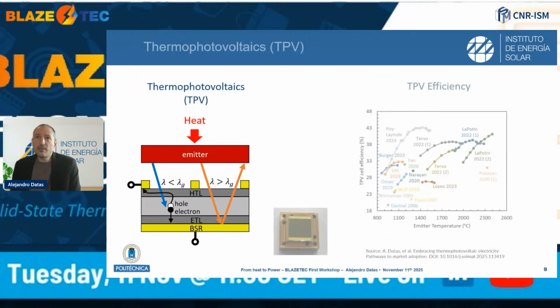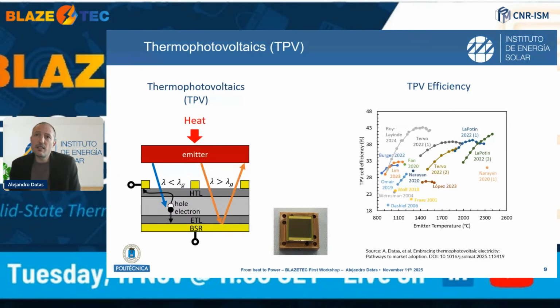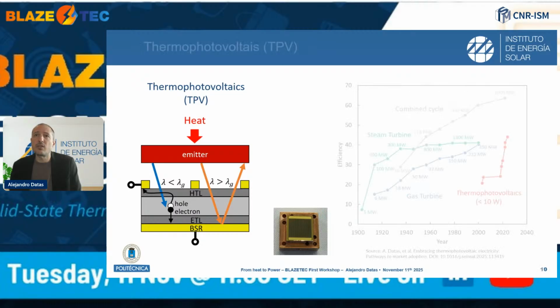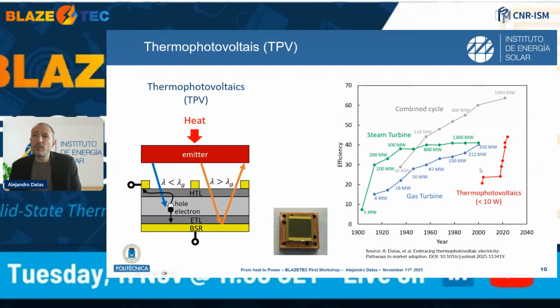And if you look at the different efficiency numbers that have been attained in the last years, you see that several authors have already surpassed 40%. Importantly, also in a wide temperature range. So typically you need very high temperatures, but you can get quite good efficiency almost at any temperature. And this is because of the high quality of the mirrors that have been developed in the last few years. If we zoom out a bit and see what this efficiency means in the context of heat engines, we see that thermophotovoltaics has already reached the efficiency levels of steam turbines or gas turbines. So this is quite a relevant milestone. Of course, it has been demonstrated at lower power levels, but still this is a really important observation.